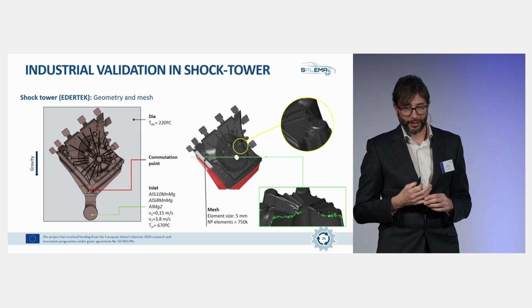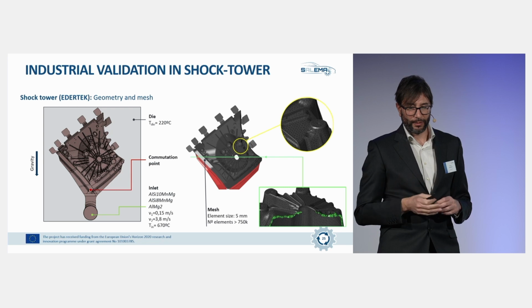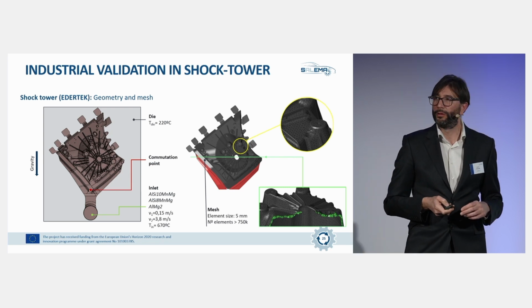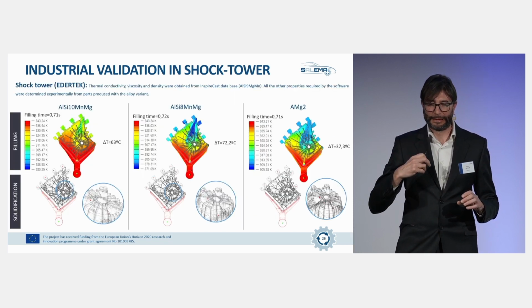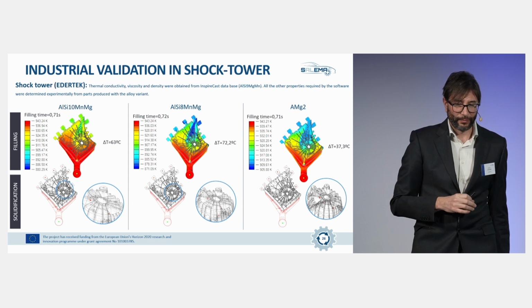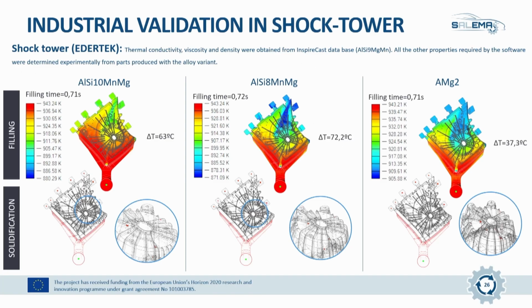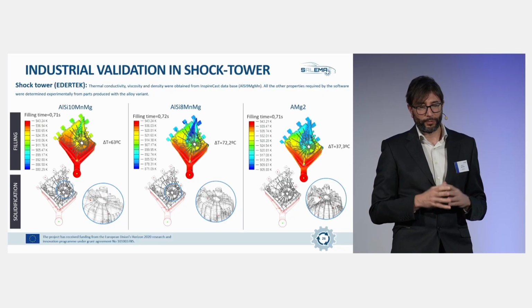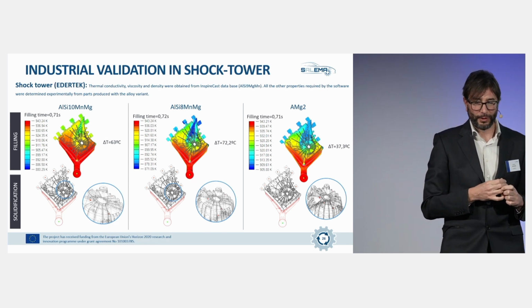Here you have the basics of the simulation we carried out, the geometry, the mesh, and the conditions. And then we had the results of the simulation. So we observed that with the partially recycled aluminum, silicon 10, manganese, magnesium alloy, it shouldn't be a problem to cast the component. Even if we had a slightly higher iron content, copper and zinc, the flowing conditions were mostly unaffected. And the filling was very similar to the base alloy.